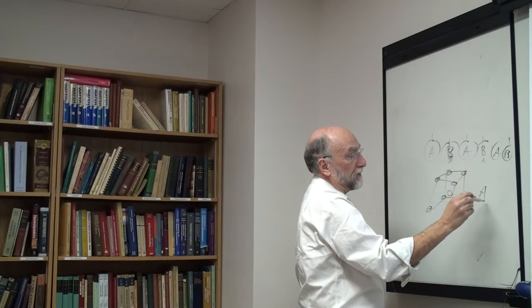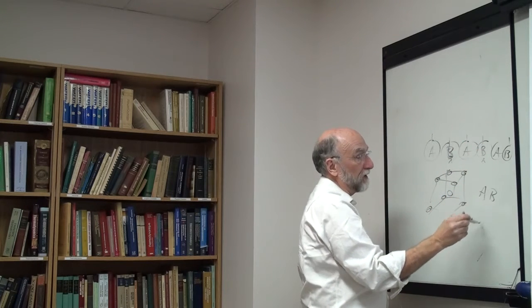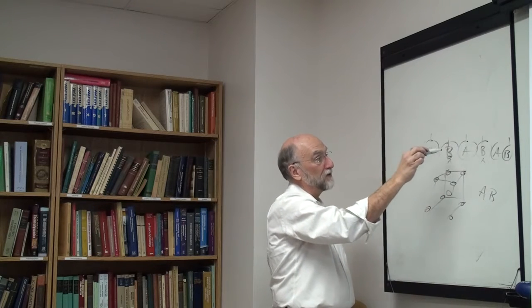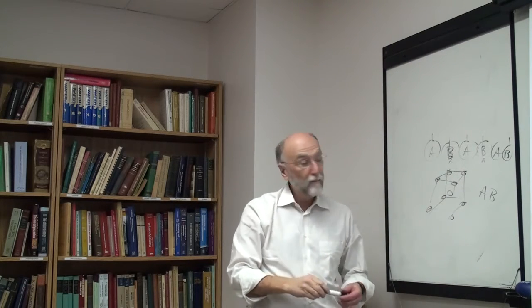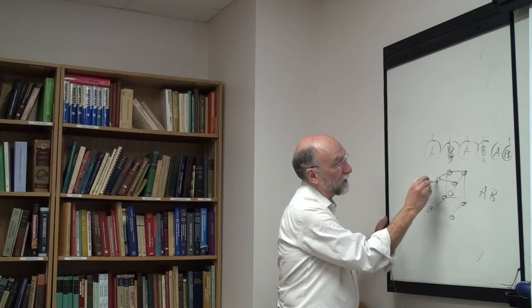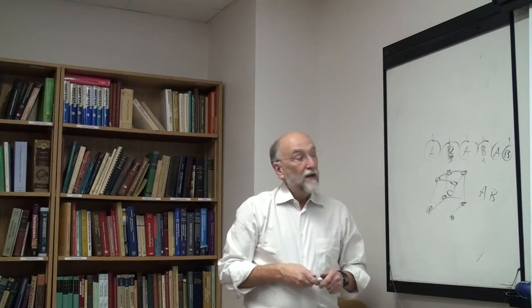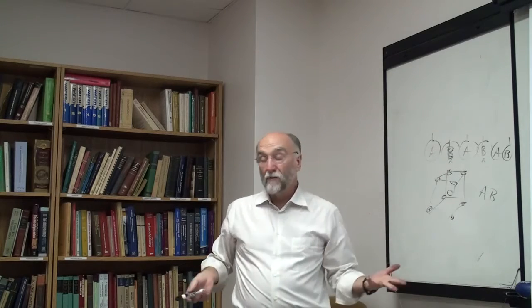Okay, I'm talking about a 50-50, A one half, B one half composition. This is the A sublattice, which is normally occupied by A, and this is the B sublattice, which is normally occupied by B. The corner sites are normally occupied by the cesiums, and the center sites are occupied by the chlorines. Now you don't have to have complete long-range order.